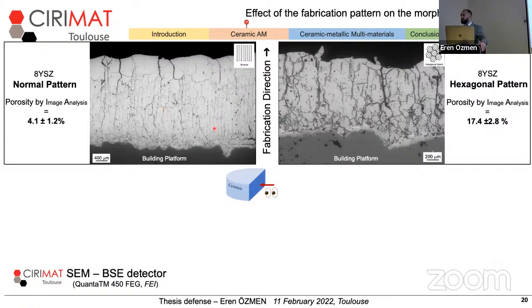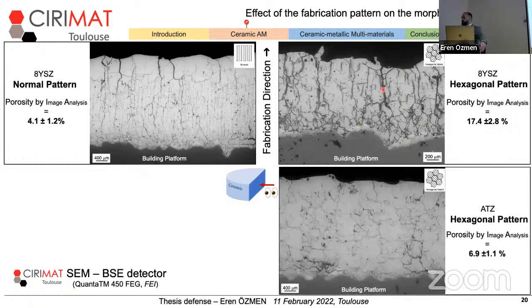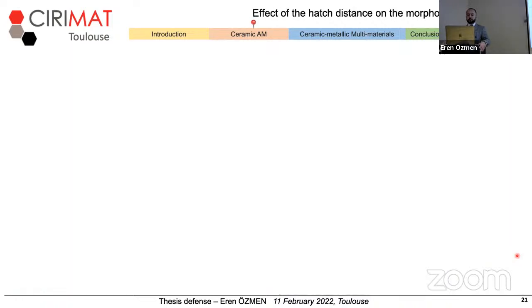And also what takes significant attention here is the cracking pattern in the two pieces. In one, the cracks are more parallel to the fabrication direction and narrower. And they show 3 different distributions in the microstructure: close to the surface, in the core, and close to the building platform. On the other hand, we have larger cracks, which go through almost the entire structure and end up at the surface. When we include the ATZ pieces fabricated with the hexagonal pattern, we see that cracking is shorter, kind of homogeneously distributed through the structure, and narrower if we consider the defects as well. So the porosity obtained for this piece was around 7%.